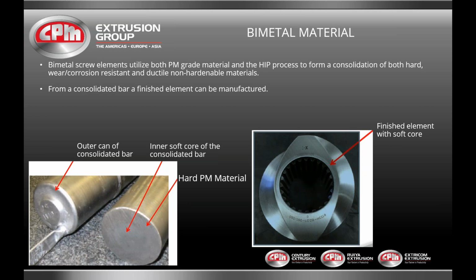In the slide, the lower left shows the consolidation as we receive it from HIP. It's got a container on the outside that contains the powder, and just to the right of that, you can see the bond line, or the difference between the two metals, the core and the outer material. The picture on the right shows a finished element with the soft core—you should be able to see the line separating the two.